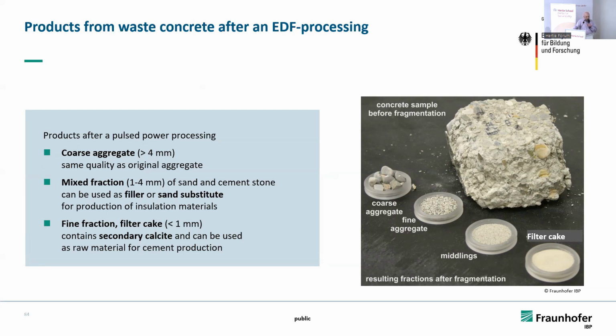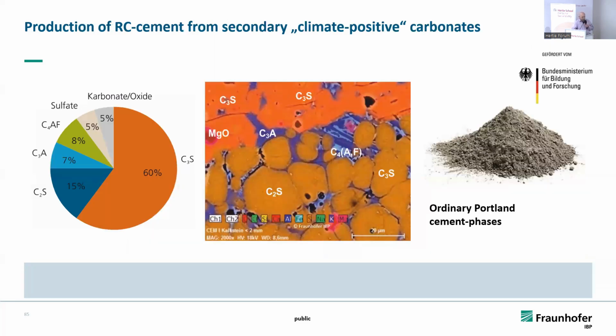So the effect is that the lightning strike releases the calcium ions in the process water. The water becomes highly alkaline, and this absorbs CO2 from the atmosphere like, let's say, a vacuum cleaner. And so in every case, the cement stone was completely carbonated afterwards. And now we can use this filter cake, which you see here on the right-hand side. We have to adapt it a little bit by chemical means, and then we can really produce again an ordinary Portland cement out of these filter cake fractions.